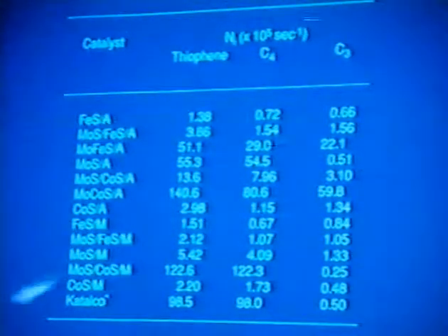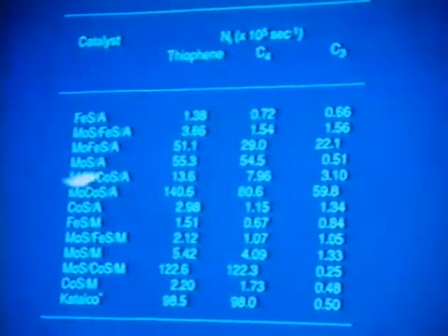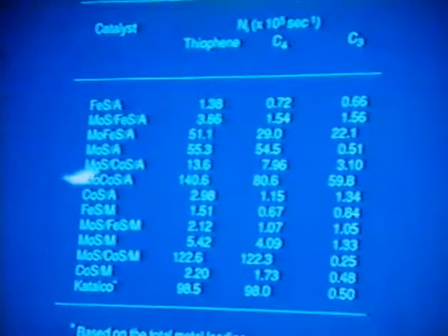estimates. The reasons why, for instance, the molybdenum cobalt on MgO responds differently than the molybdenum cobalt on alumina is not well understood. We expected the opposite. It's typically noticed and reported in the literature that cobalt sulfides or cobalt will tend to promote the activity of molybdenum sulfides.